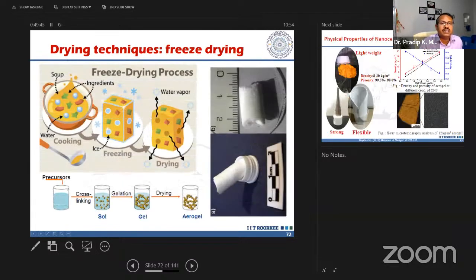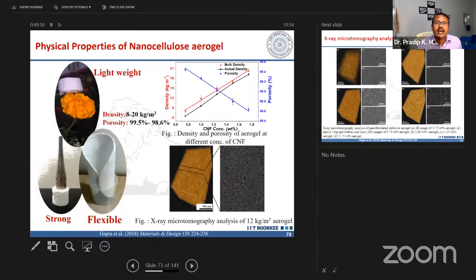This is the drying process we have utilized, the freeze drying process. After that, we are getting a density of 8 to 20 kg per cubic meter and porosity of 99.5% to 98.6%. It is very strong because it can withstand more than 1 kilo of weight. It is also very flexible, so we can put it in a cup. And this is the micro-tomography analysis, showing a monolithic structure inside the aerogel material which remains the same.